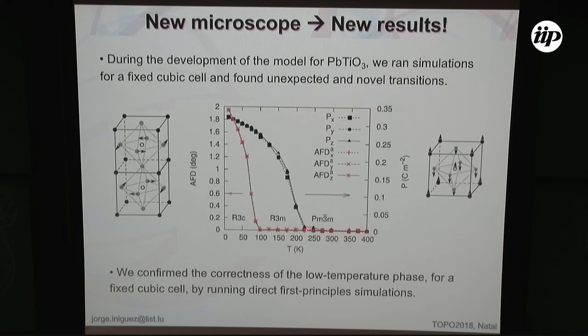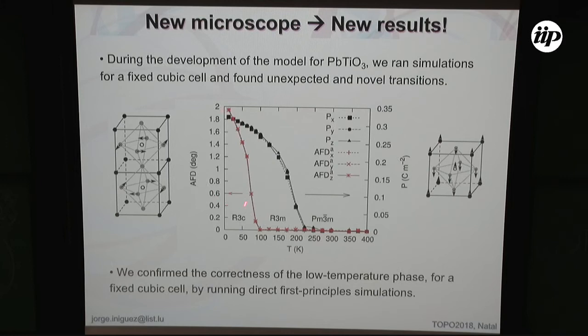Under this elastic constraint, at some temperature there is a transition from paraelectric to a ferroelectric phase. The polarization develops, but now to a rhombohedral phase rather than tetragonal. That was already known from earlier calculations. But what is interesting is that at even lower temperature there is a second transition involving rotations of the oxygen octahedra — and this had never been seen before, not ab initio and not experimentally, as these are difficult conditions to attain. Our model was predicting this.